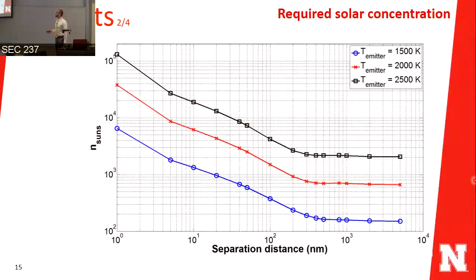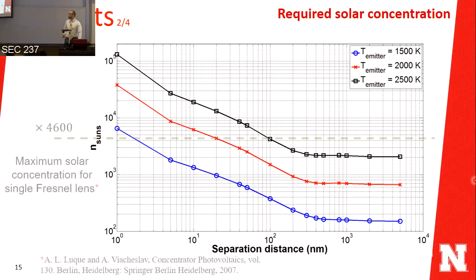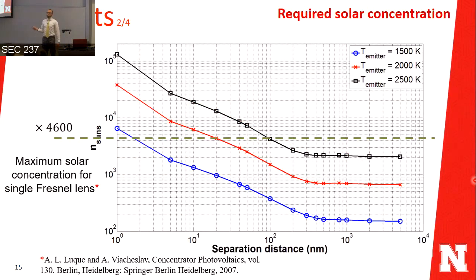The second piece of results I'd like to share is the solar concentration on the y-axis versus separation distance. Of course, the less the separation distance, the higher the energy required to keep the emitter at constant temperature, and the more solar concentration needed. So the limitation for solar concentration will be the concentration of a single Fresnel lens, which is 4,600. Below this, you can achieve that system. So it also imposes a limitation at high emitter temperature, but lower than 2,500 K will not be a limitation for your system.